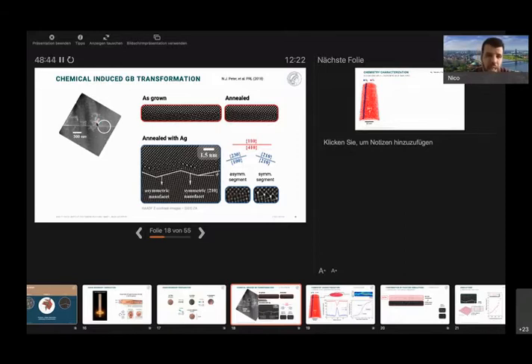It could be. I don't know, because, you know, silver is a pretty big atom compared to copper. And I think it depends a little bit on the dislocation core, how big it is, if silver is easily fitting in. But in this case, dislocations are very close to the boundary. I would think it's energetically much more favorable to go to the boundary than to the dislocation.